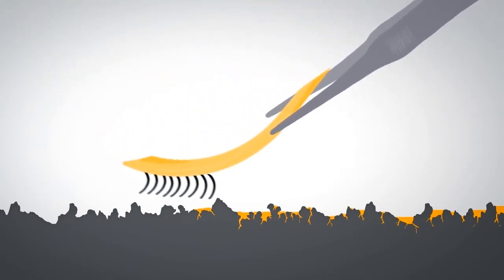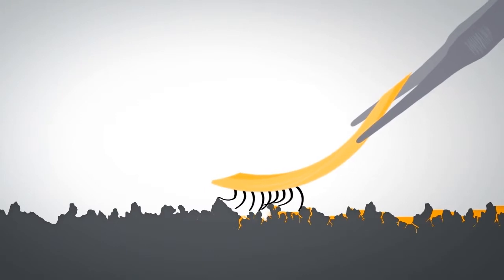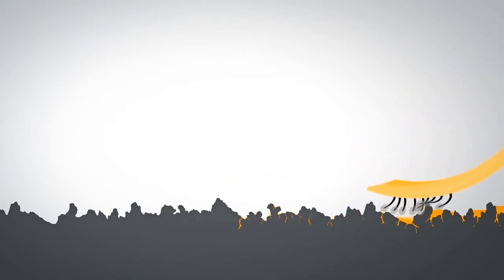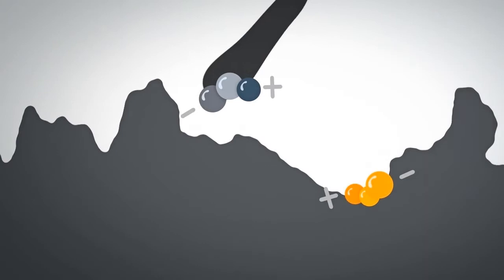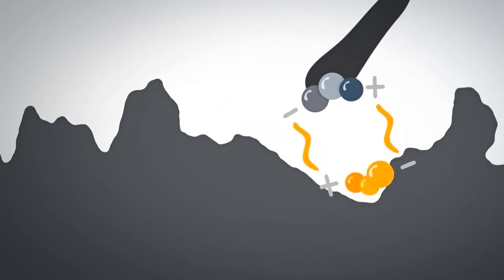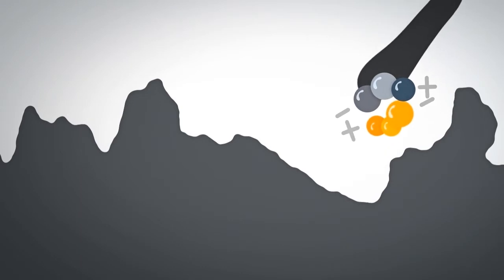It has individual fingers that can move independently, but the ends of the polymers have special chemical head groups attached. And those chemical groups we put on the ends of the polymer fingers in our swabs have very strong chemical interactions with the residues, and they're very specific for the chemistry of the residue. So when they get close together, they attract and hold the residue very closely.